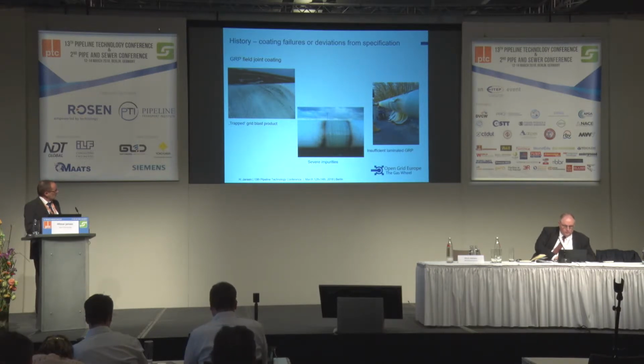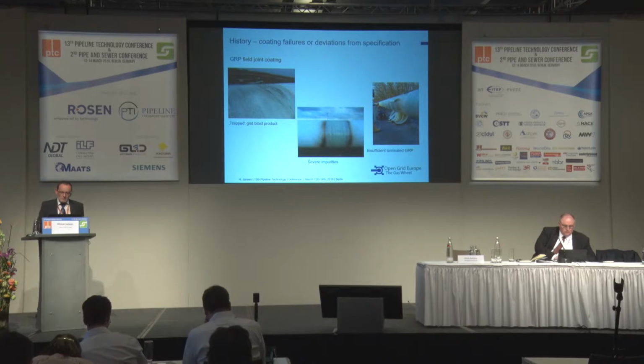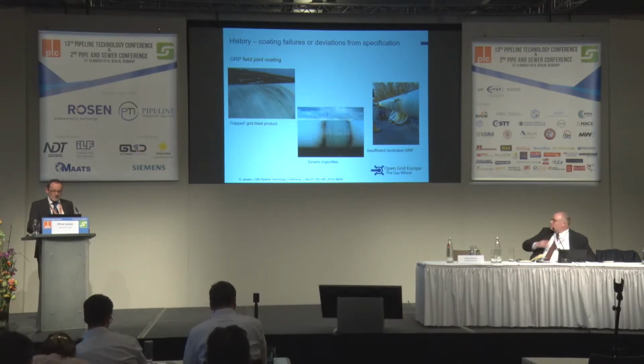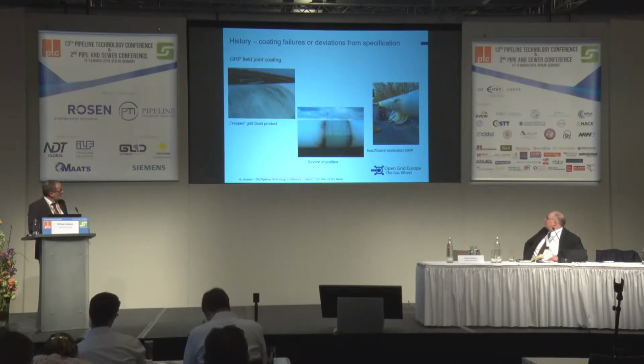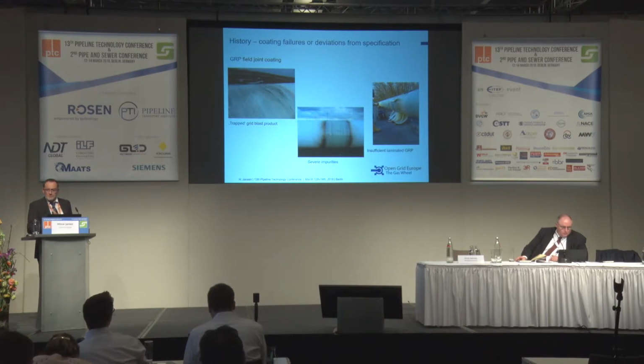Insufficiently laminated GRP: you can see pieces of the glass fiber that are totally loose from the field joint area. Here no epoxy has been laminated at all, with a completely insufficient result of the field joint coating.